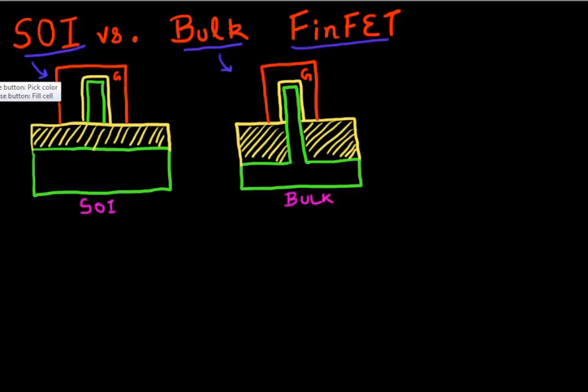So as I described to you in one of the videos earlier, the way you make FinFET or the way you define fins in your SOI substrate is that you have a fixed thickness of your silicon, and then you essentially etch that to describe your fin. And so that way your fin height is determined by your silicon thickness to start with, and you get these fins which have very uniform fin height. Or in other words, their variation in their fin height is pretty low.